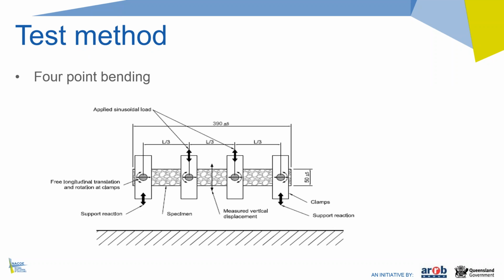That brings me to the test method. For those of you not familiar with the four-point bending test method, all we do is produce an asphalt beam in the laboratory. We hold it at the ends, and then we introduce a sinusoidal displacement load on the inner clamps and measure the modulus at a low strain value.